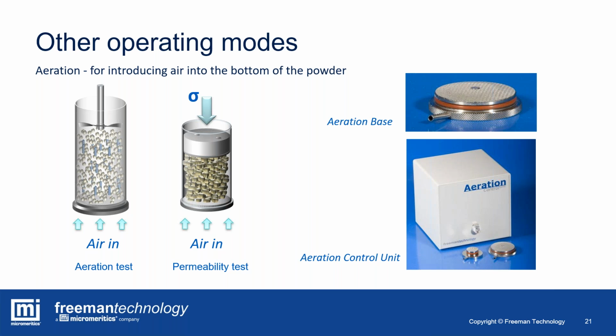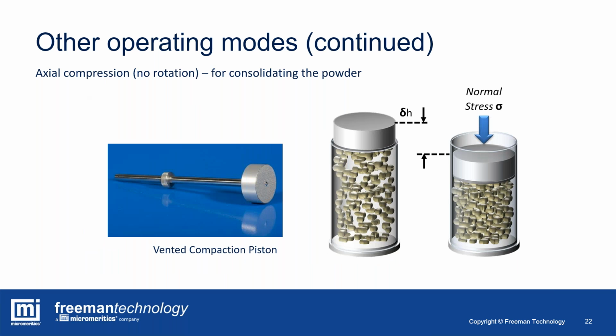Alternatively, you can change the blade for a piston, a vented piston, which allows air to escape through the surface. And we can measure the air pressure differential across that powder bed for a given consolidation stress and for a given gas velocity. And that gives us a measurement of the permeability of the powder. We can use that same piston, but without an air supply, to simply measure compressibility, so changes in density as a function of applied stress.